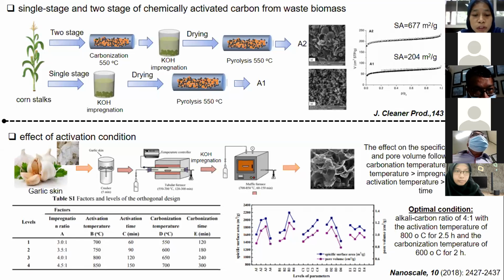While for the activation temperature effect, initially, as the temperature increases, more energy is provided for the reaction and more carbon atoms at the active sites are consumed to form pores, which makes the specific surface area and the pore volume gradually increase. However, when the temperature increases further, the diffusion rate of potassium ions increases, accelerating the reaction rate of carbon atoms at the active sites, ablating the micropores and collapsing the carbon skeleton. And it leads to a decrease of the specific surface area and the pore volume.